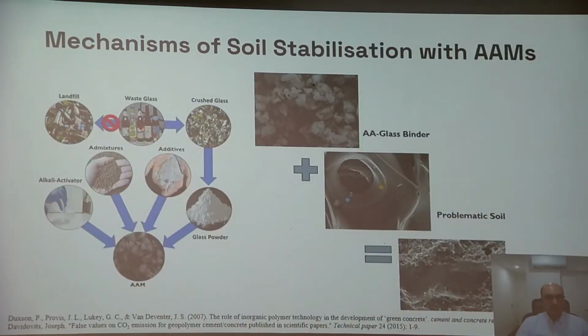As you see here, alkali activated binder stabilizes soil through a combination of chemical and physical mechanisms. The alkaline activator reacts with the waste glass to form a strong matrix that enhances the mechanical property and durability of the stabilized soil. As you see here, the waste glass could be sent to landfill or could be crushed, and then the glass powder is created from the crushed glass to be combined with alkali activator, admixtures and additive to create the alkali activated material or the binder.